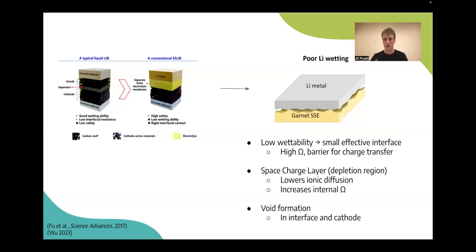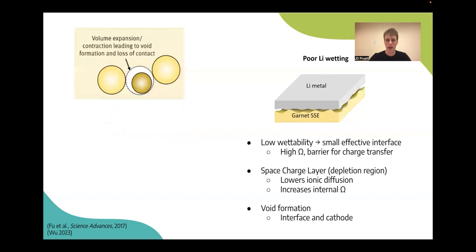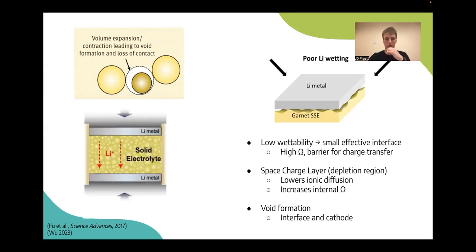As we cycle the battery, it goes through maybe different weather conditions. We're going to have expansion and contraction due to temperature increases and decreases in that electrolyte. And what can happen is the electrolyte can actually start shrinking away from the anode, and we get these spaces here. The issue with that is the same as the wettability problem. We would get high resistances and it's very difficult for ions to be transferred in that scenario where there's not good contact between the anode and the electrolyte.